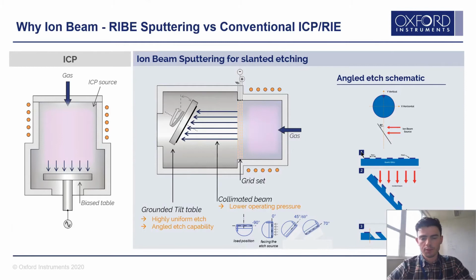In ion beam sputtering, we've separated off the plasma generation from the substrate chamber. They're two different areas. The plasma is generated in the same way as an ICP, but then using a series of grids with different voltages, we accelerate and collimate a beam of ions. These ions now have a direction of travel that they're not going to deviate from. So now we can, as on the right, move our substrate around, and get different effects off the orthogonal direction. And this leads us to be able to do things like slanted and blazed grating. So that's why we have to use ion beam for this technique.